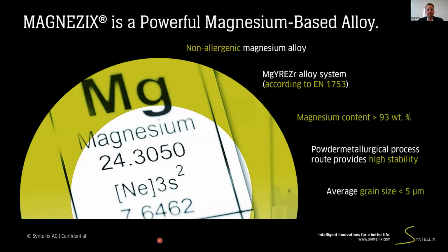Syntellix's success with biodegradable magnesium-based implants bases on its innovative material technology. The material, which Syntellix calls Magnezix, provides high mechanical strength until fracture healing, but will biodegrade afterwards. It bases on a non-allergenic magnesium alloy, Mg, YREZr, or WE43 following ASTM, with a magnesium content greater than 93% by weight. The alloying elements, zirconium, neodymium, and yttrium, in combination with a powder metallurgical process route, provide high stability due to a very fine-grained microstructure with an average grain size smaller than 5 microns.